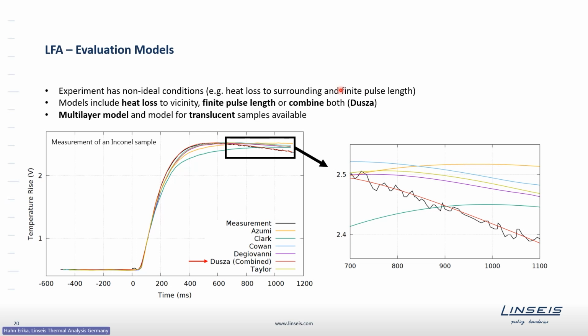thinner and highly conductive samples, where the measurement time is very low and must be related to the time of the pulse. The pulse itself, so the xenon lamp pulse or the laser flash pulse, is in a range of a few or 1 millisecond, just for your information.